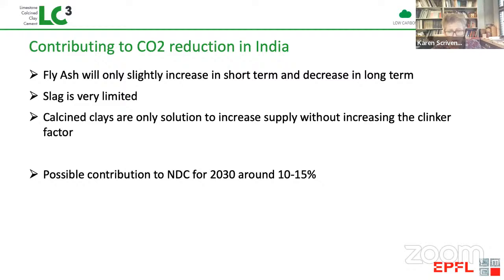Agreement. Even though fly ash is very abundant, it's unlikely to increase in the short term. And in the long term, it will certainly decrease because India as well has committed to phasing out use of coal. Slag is and will remain very limited, and therefore calcined clays are the only solution we have to increase supply without increasing the clinker factor.